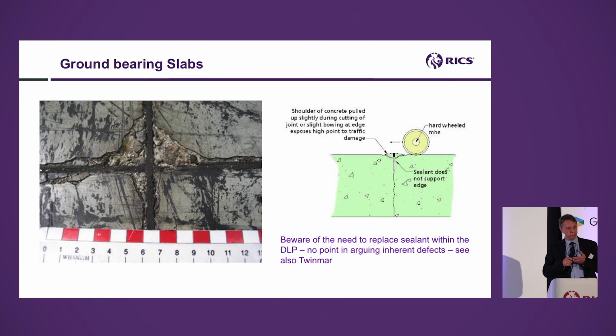What is supposed to happen is that at the end of the defects liability period, there should be a provision in the contract, one hopes, if it's specified correctly, for the contractor to go in and remove the initial flexible sealant and replace it with something harder, what's called shore hardness is better. Now, that didn't happen in this case, so the tenant was left with the original flexible sealant that should have been replaced. He still had it.